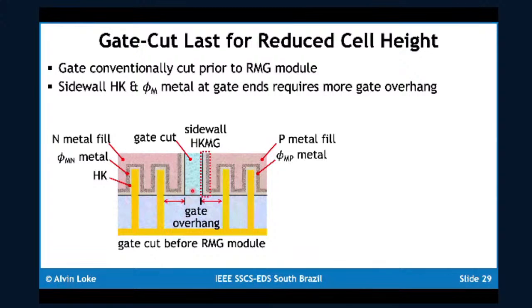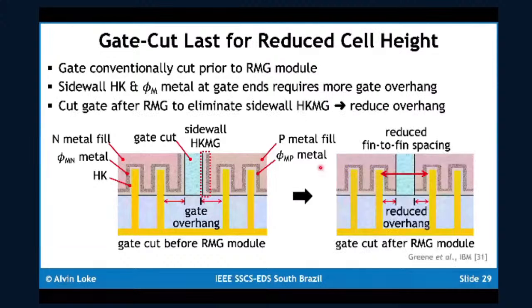If you were to essentially keep the gate cut until much later, where you deposit the HighK metal gate module first, and then cut and break the gate in one step, that allows you to reduce the overhang outside of the fins, allowing you to reduce the fin-to-fin spacing, which in turn reduces your standard cell height and standard cell area once again.